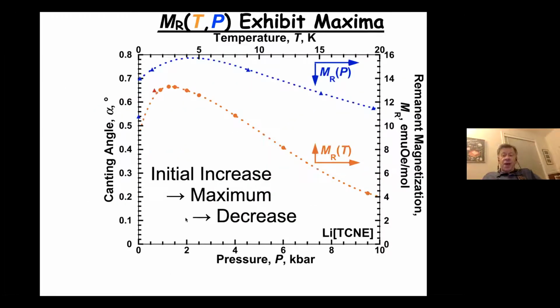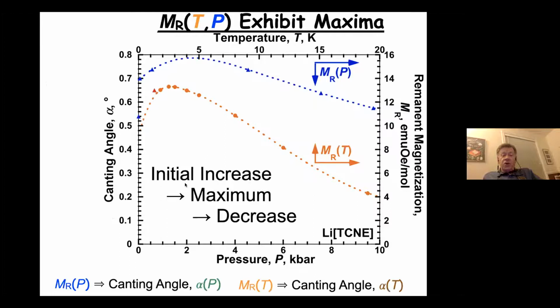And here we look at the remnant magnetization as a function of temperature and pressure. And you can see in both cases, initially they're at some finite value, depending on the scale you're looking at. And then it rises with a small increase in pressure or a small increase in temperature, reaching a maximum in both cases. And then on further pressure increase or temperature increase, the value decreases, and in fact, in both cases, are lower than the original value at ambient pressure and temperature as we have it. So we have the remnant magnetization as a function of pressure and temperature.